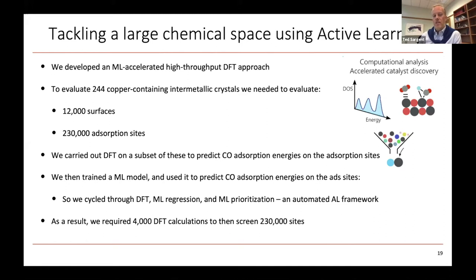And so working with Zach and his team, we looked at whether we could perform DFT just on a subset of these adsorption sites. We ended up doing full DFT on about 4,000 sites. But we used the data from those DFT to train up an ML algorithm, and we showed we were able to accurately predict the behavior of the 230,000 adsorption sites. So about a 50x multiplier in acceleration relative to having done everything with brute force DFT. And it was very much an automated learning framework in that we actually cycled through the DFT, the ML regression, and then the prioritization as well with the aid of the ML approach.